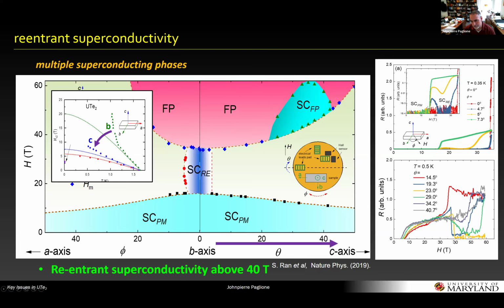So this was the first measurement of resistance, and there's some TDO measurements, but there have been magnetocaloric experiments at Los Alamos that are consistent with this being a bulk superconducting state. So it's hard to do other experiments up here, but we're trying to think of other ways to probe the superconducting state up here. It's at this obscure angle that seems to be about 30 degrees or so, which doesn't seem to point in any particular direction, especially because of the width of this.